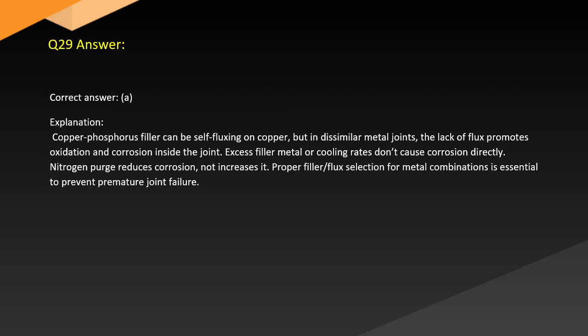Answer. Correct answer: A. Explanation. Copper phosphorus filler can be self-fluxing on copper, but in dissimilar metal joints, the lack of flux promotes oxidation and corrosion inside the joint. Excess filler metal or cooling rates don't cause corrosion directly. Nitrogen purge reduces corrosion, not increases it. Proper filler and flux selection for metal combinations is essential to prevent premature joint failure.